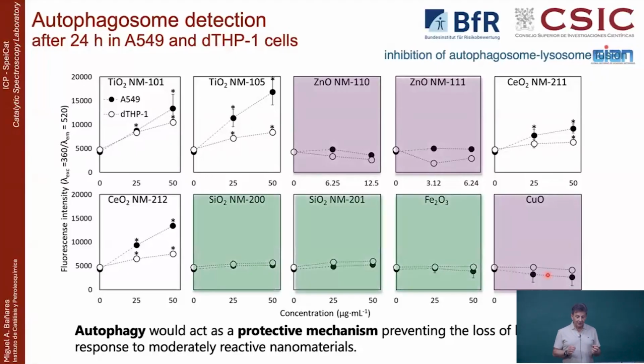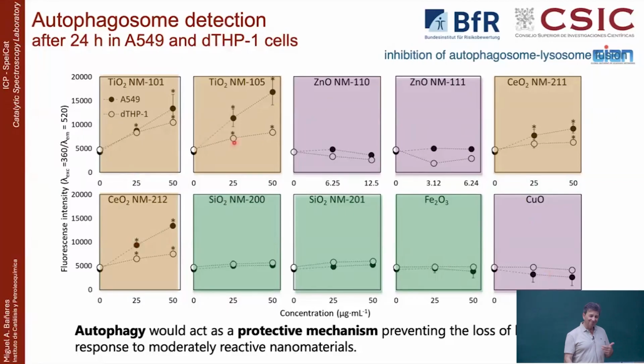When you expose the cells to non-reactive or very little reactive materials, the autophagosome is not triggered, they do not die, but they don't need the autophagosome. But for the intermediate reactivity materials, ceria and titania, the cells do not die, but the autophagosome is triggered, which is basically telling you that the system is compensating for a partial damage. So the answer of the system is, okay, the bad ones are killing them, no reactions. The good ones are not doing anything because they have no reactivity, there is no need to compensate. And those with an intermediate reactivity don't kill you, but they are ugly, they are nasty, they are doing something that is affecting you, but the cells are compensating for it. So there is damage that is being compensated. The cells do not die, but that doesn't mean that they do not suffer.